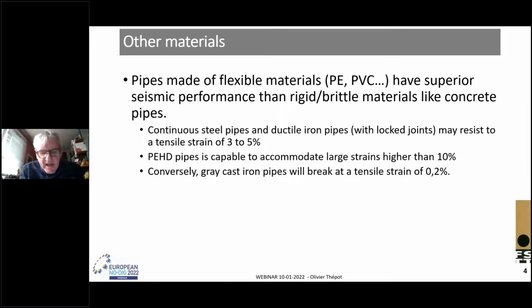It is commonly accepted that pipes made of flexible material like PE or PVC have superior seismic performance than rigid materials like concrete or grey cast iron pipes. Continuous steel pipes and ductile iron pipes with locked joints may resist a tensile strain of 3 to 5%. PE pipes are capable of accommodating large strains higher than 10%. Conversely, grey cast iron pipes will break at a tensile strain of only 0.2%.